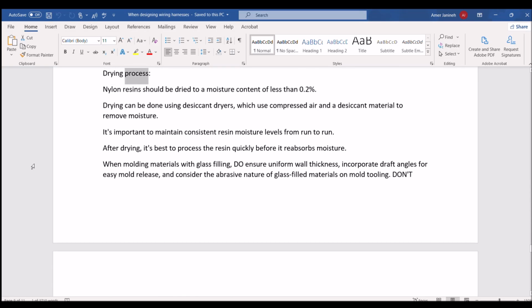Drying process. Nylon resins should be dried to a moisture content of less than 0.2%. Drying can be done using desiccant dryers, which use compressed air and a desiccant material to remove moisture. It's important to maintain consistent resin moisture levels from run to run. After drying, it's best to process the resin quickly before it reabsorbs moisture.